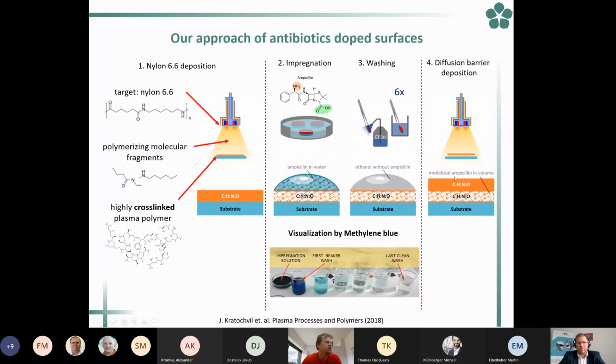We try to control the release by this protecting layer, or what we used to call a barrier layer. So according to the thickness, we are able to control the release. If you want to hear some numbers, without the barrier film the release is usually within some hours. The bigger shock is, of course, at the beginning. Then we observed more or less an exponential decrease, and depending on the amount, due to the thickness we are able to store the ampicillin, which can then be released for some days. With a film thickness of 300 nanometers, after 5 days all the ampicillin is already released.